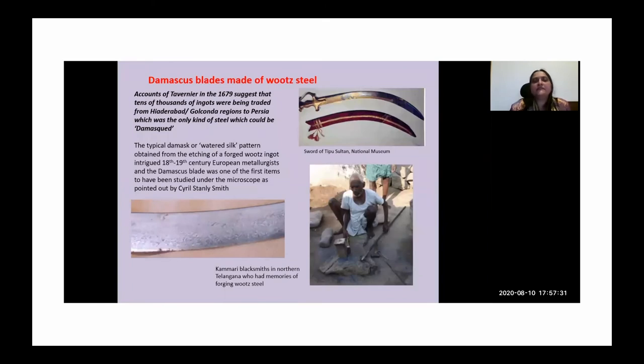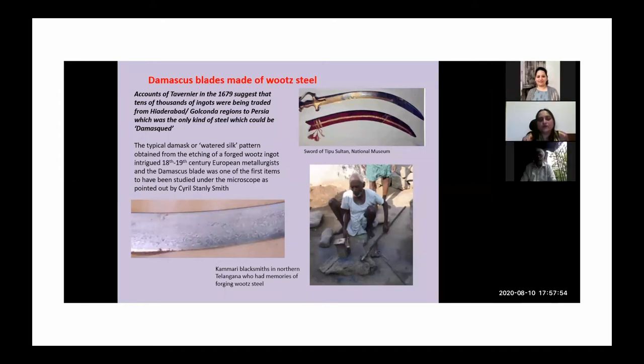Now, why that particular microstructure is significant also is because wootz was famous for making these Damascus blades. And these fabled Damascus blades were well known for the patterns that they had. That pattern typically comes from the forging and the etching of the wootz ingot, where you have these alternating wavy patterns of dark pearlite and light cementite, this very wavy pattern which was described as damask in Arabic and so on.